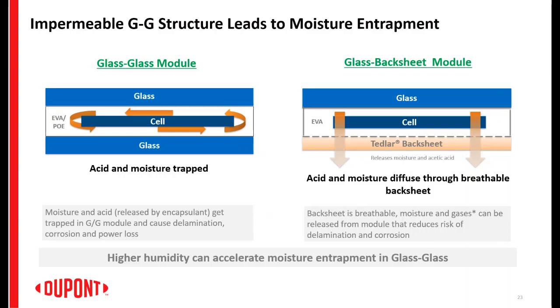While that is true, the moisture would still gradually go inside the module through the edges of glass structures. Moreover, the encapsulant used in the module would release gases over time as well. And since a glass module is nearly impermeable, it won't allow anything to go outside. The moisture and gases which are released get entrapped inside the module, and over a period of time that would cause delamination and corrosion, which eventually would lead to high power loss.